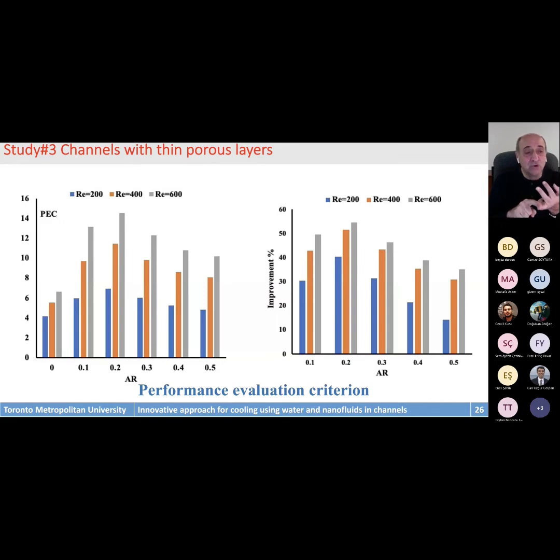On the other hand, it also has an optimum pressure drop. So the ratio between both of them is the best candidate, aspect ratio equal to 0.2. So this is a purely numerical model after we calibrated the experimental work.